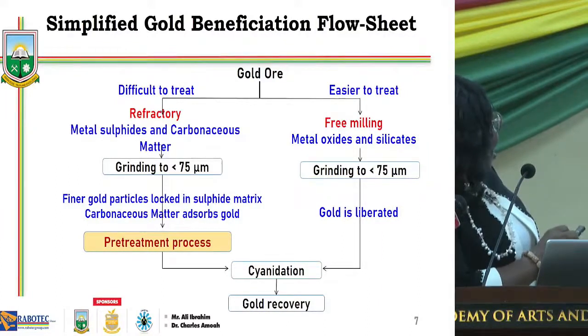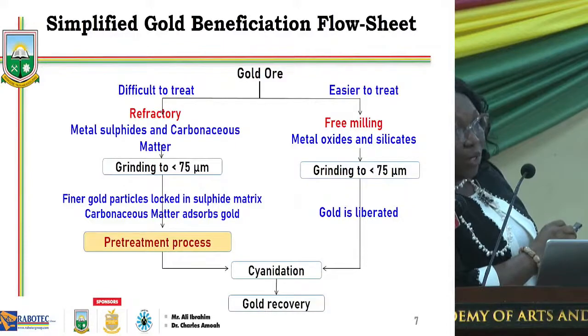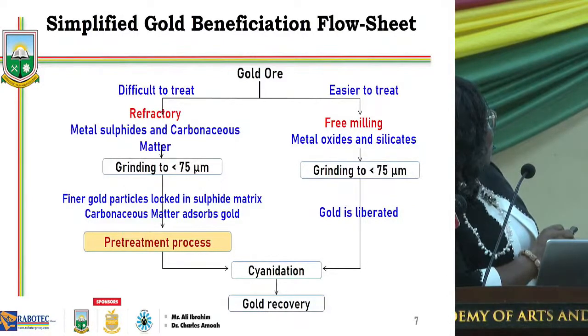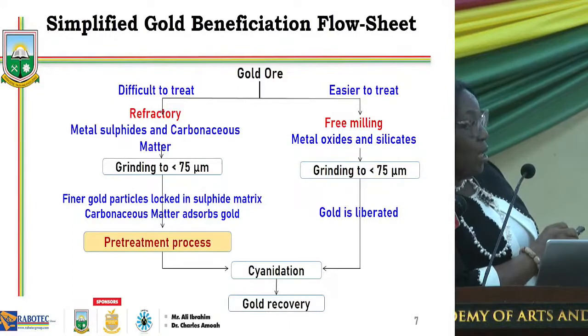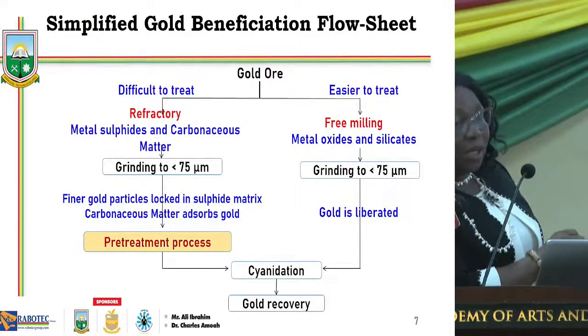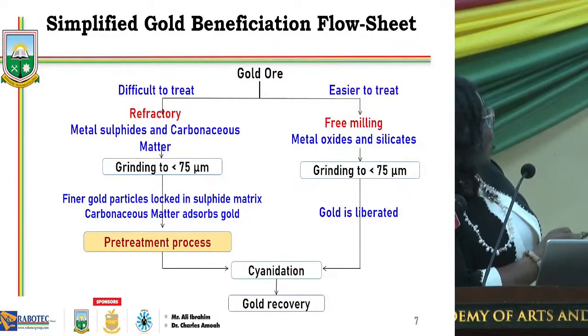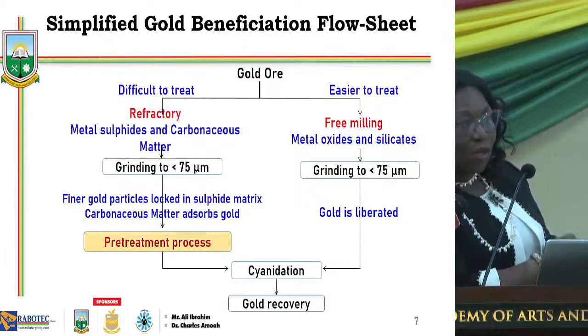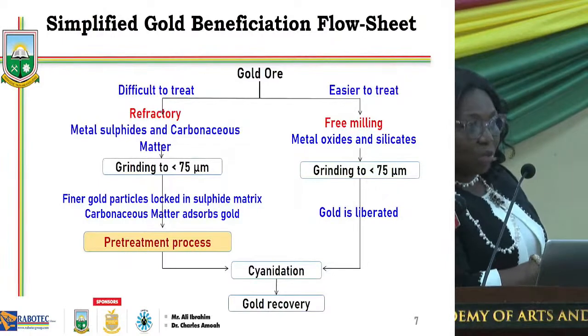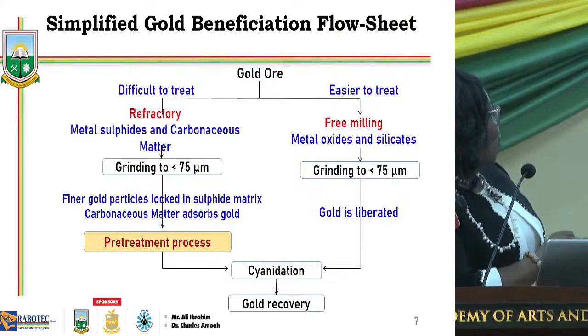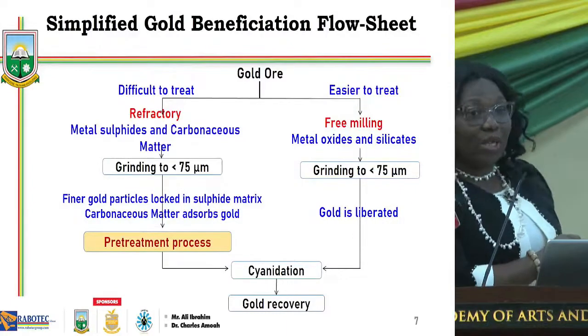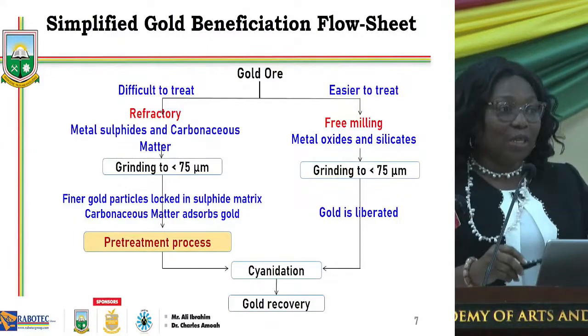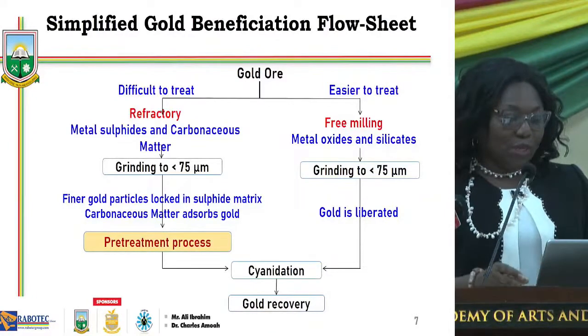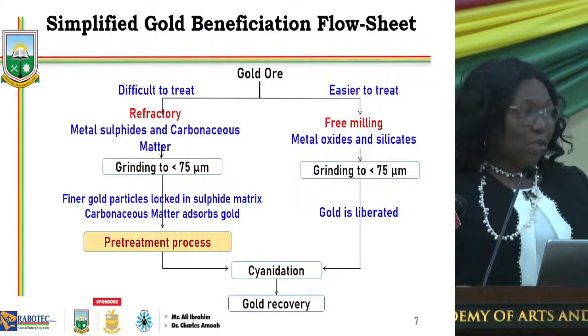On the left-hand side, we have the difficult to treat, which is called refractory gold ores. The refractory ores contain sulfides and carbonaceous matter as the most important refractory components to us. And even after grinding so fine, the gold is still locked up in the sulfides, and so it is not available for dissolution. For the carbonaceous matter, the main problem is that when we start dissolving the gold, the carbonaceous matter is able to pick the gold back into the solid state, and that will lead to losses.